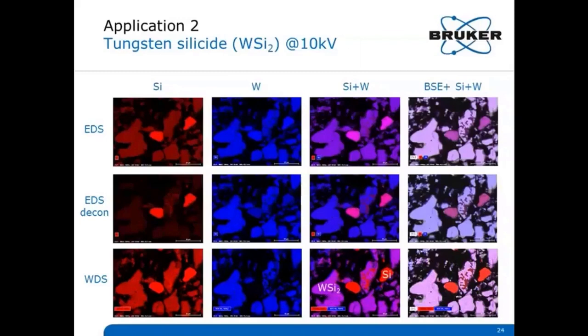The two particles are actually pure silicon chips in the sample, which do not contain any tungsten. And the majority of the particles surrounding these are tungsten silicide. So in conclusion, WDS mapping better images the element content and relative proportions.